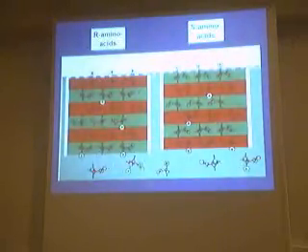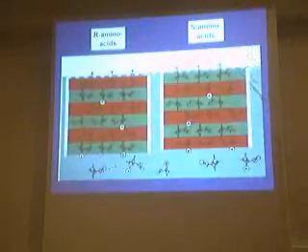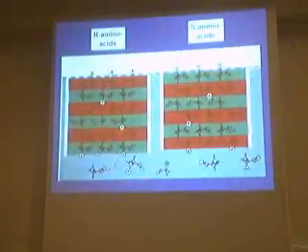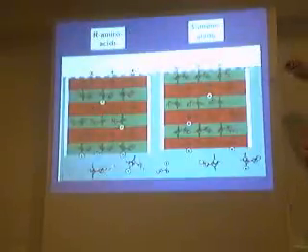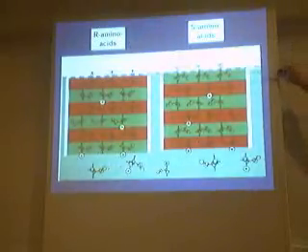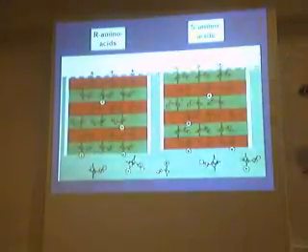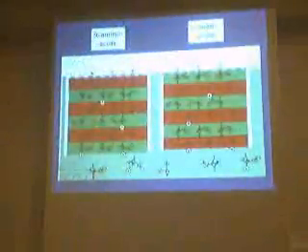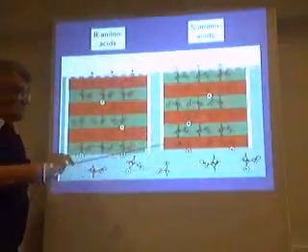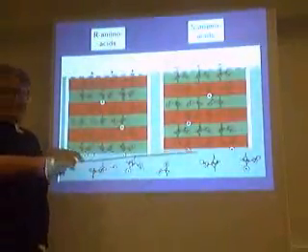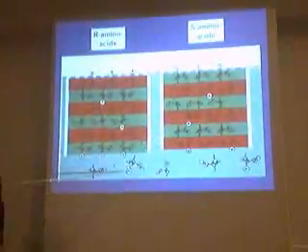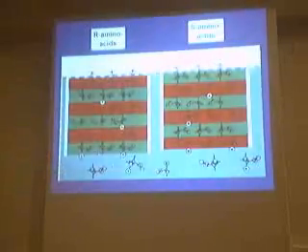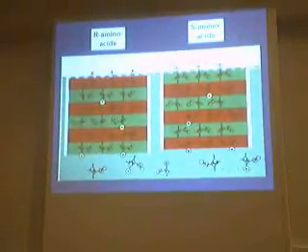Okay. And then what we expected was that these species, which are formed at the water interface, must form a crystalline aggregate, where the polar head groups at the water interface will induce nucleation. If you start with the S amino acid, they must start from one face, and then the crystal will grow in one direction. Whereas if you start with the R amino acid, they will grow in the other direction. Okay? And if they start growing that way, they can pick from the solution molecules of opposite chirality, and if they pick molecules of opposite chirality, they enrich the solution with the glycine, and then the glycine will go back to the surface, and this glycine will now induce additional orientation of the next crystals, and the next crystal will grow with the same orientation as the first one. Okay?